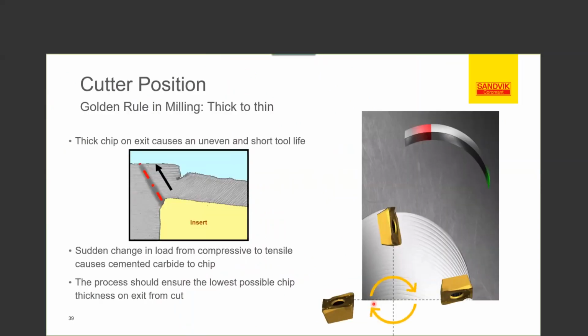So in essence, what's happening during an operation is a cyclical operation as the inserts spin in a milling cutter. As it goes into a cut, we create a thick chip and a thin chip on exit. The problem is if we have a thick chip on exit, and you can see from the animation right here, the yellow being the insert, we get a tremendous amount of tensile stress right here. What happens is we actually break out. When we break out, the insert will fracture an edge, and we want to be very careful of that.